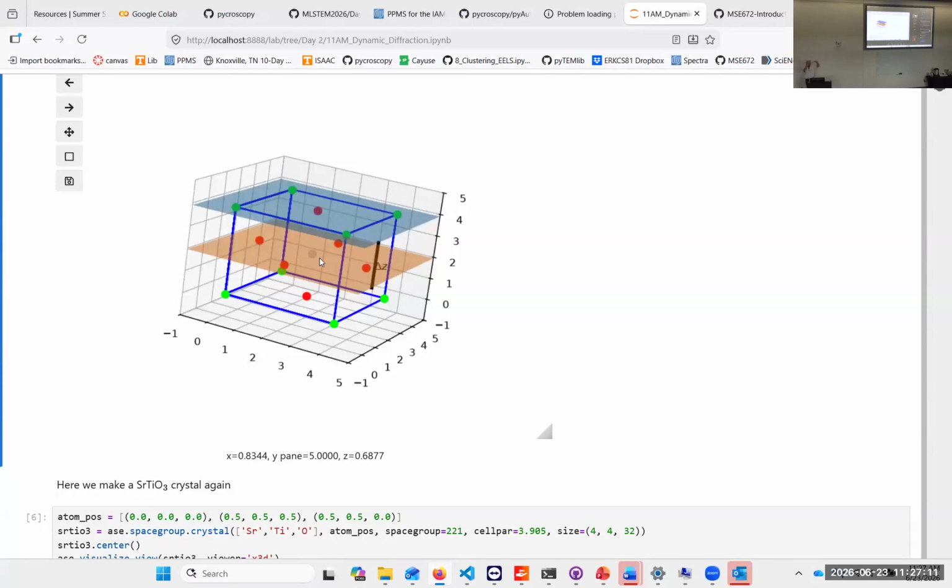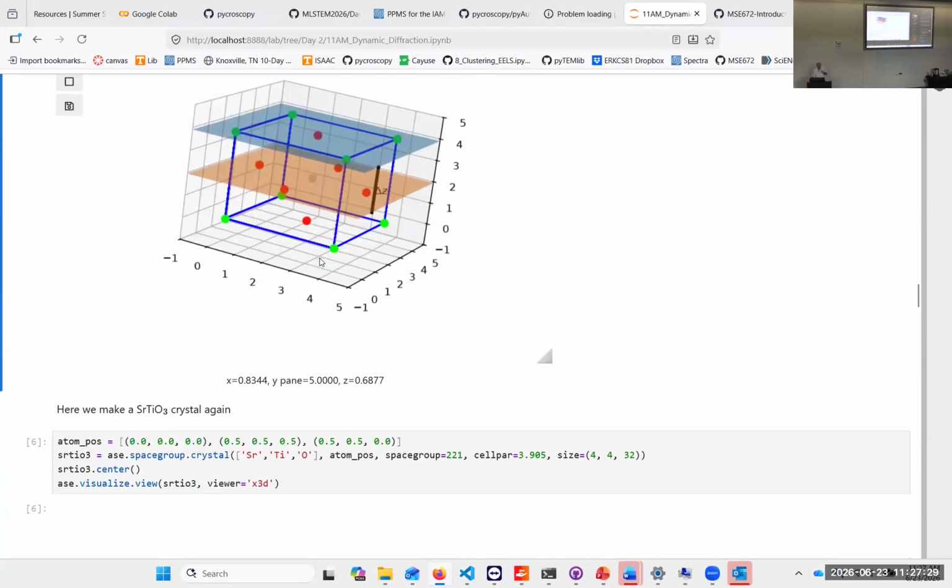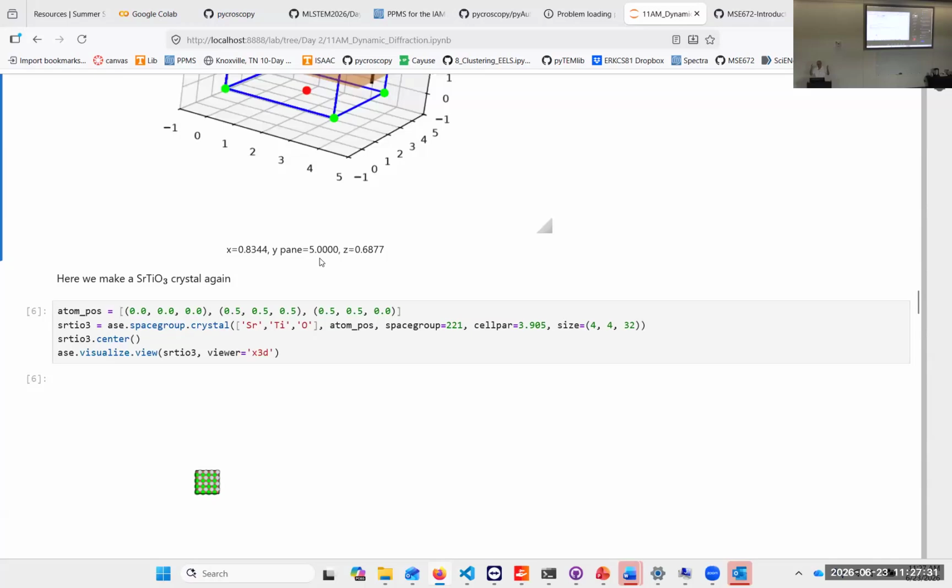So we go reciprocal space, path length, real space, then we scatter again, reciprocal space. We do a lot of Fourier transforms as we go through that, for each layer. So we have a scattering part and the transport part.